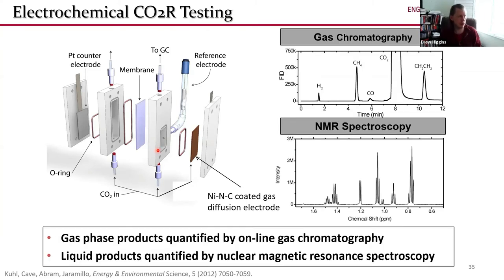So this is what a typical GC spectra and a typical NMR spectra may look like, where the GC detects things like methane, ethylene, carbon monoxide, and NMR can detect things like ethanol, formic acid, acetaldehyde. I'm not going to talk too much about NMR because, as I mentioned, these nickel nitrogen carbon catalysts produce largely carbon monoxide, so a gas phase product. So pretty much everything that I'm going to be showing is from the GC analyses.